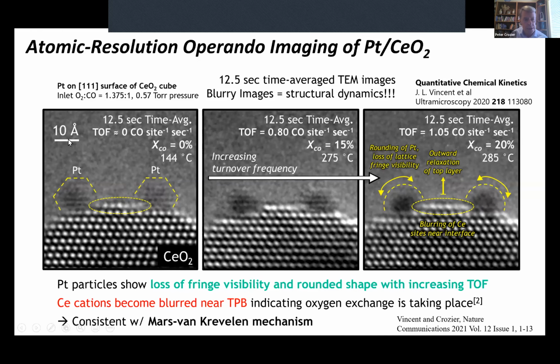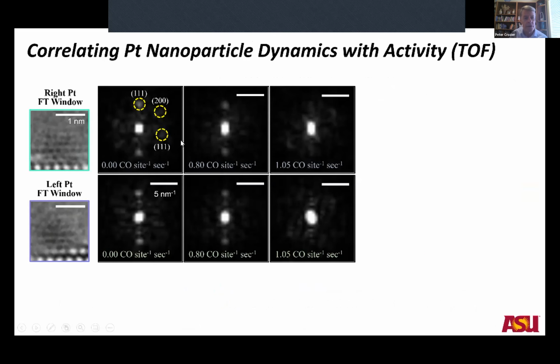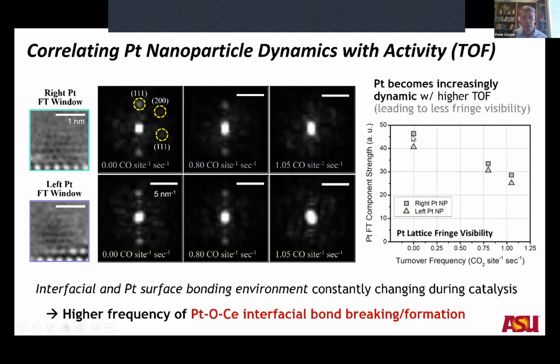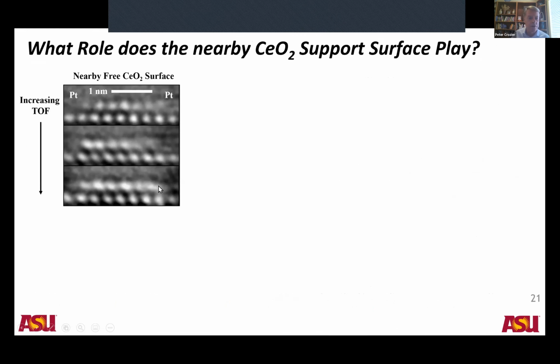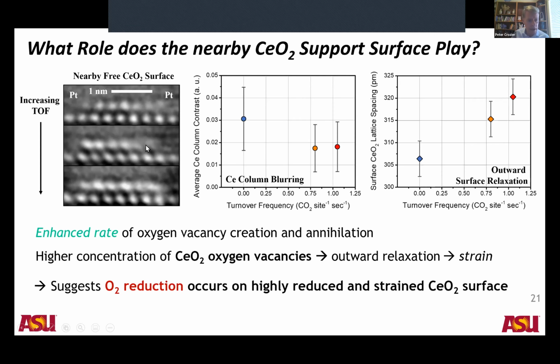So Josh went and processed these, and again, I won't go through the details here. He used Fourier techniques to measure the dynamics on the platinum nanoparticles and found that they became more dynamic as the turnover frequency increased. So there was a definite correlation between dynamics in the platinum nanoparticle and catalytic activity for CO oxidation. And then he also quantified by measuring the visibility of the fringes associated with the ceria at the surface here. And he was able to show that that visibility also correlates directly with catalytic turnover frequency.